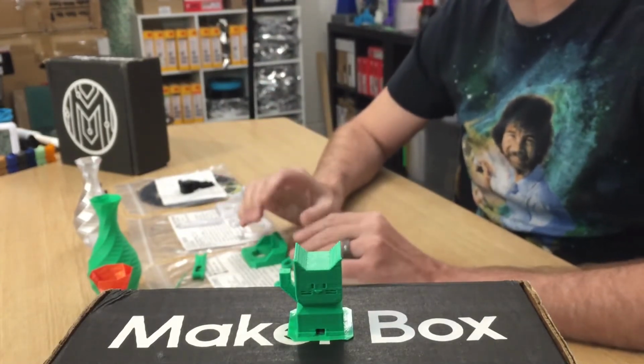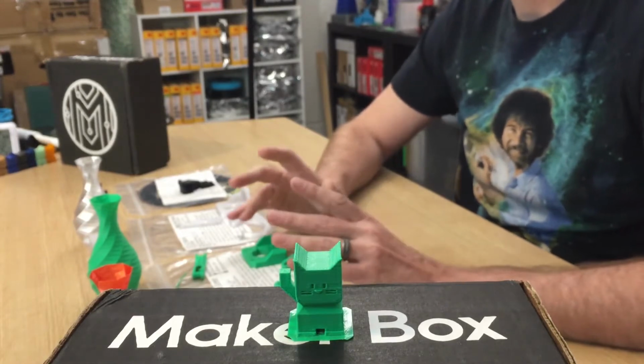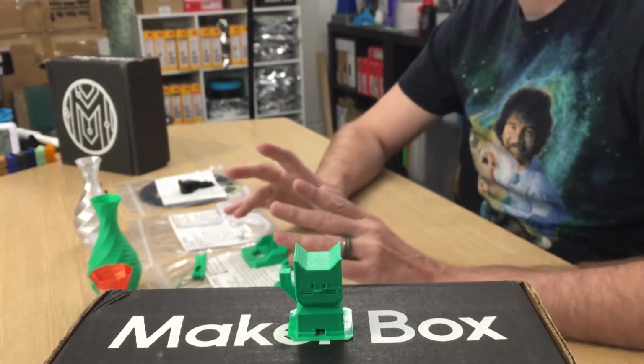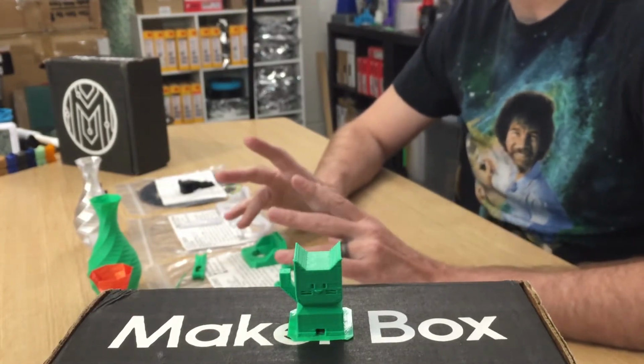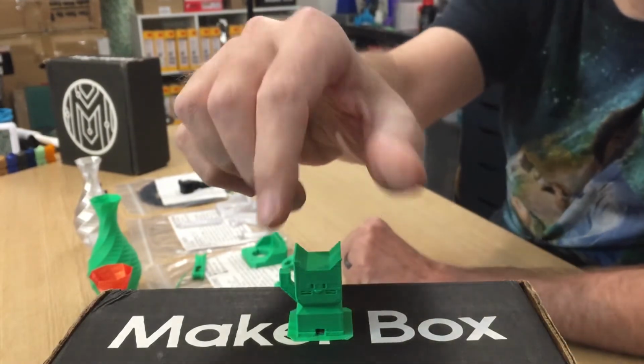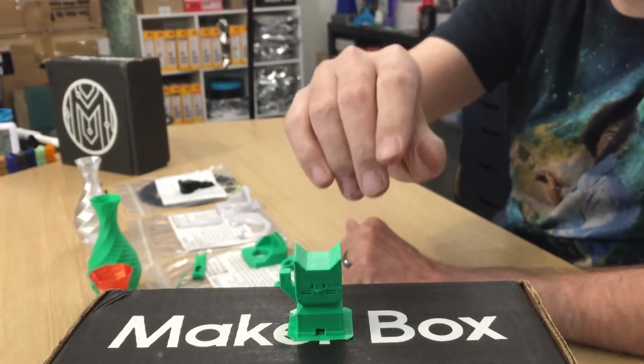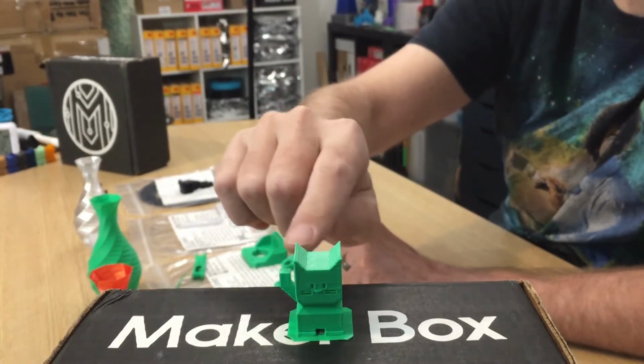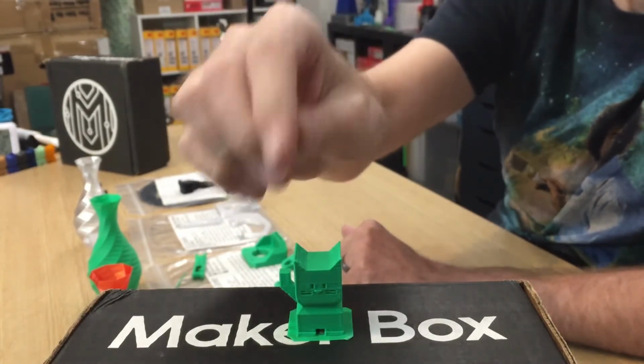The temperature range here is 190 to 230, and I believe I started at 215, and I did end up back down at 205 with good layer adhesion, no problems whatsoever. But the Cali Cat turned out great even at 215. And there's minimal stringing on the tail, which is nominal, easily fixed.